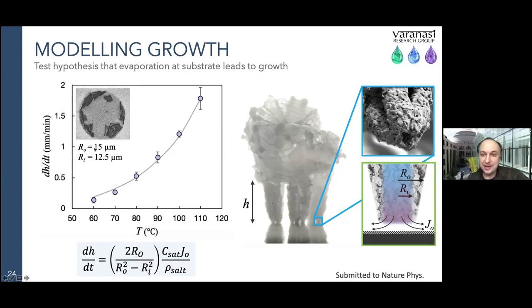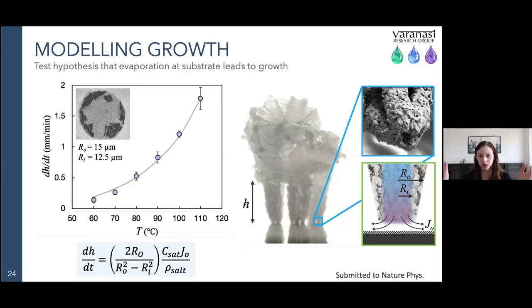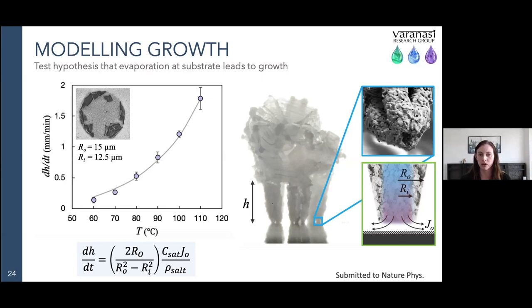A question from Ramiz Iqbal: in the first part describing the fingering instability, why don't the crystals come closer and aggregate? Normally for microparticles one might see close packing after complete evaporation. In the colloidal case you have a liquid bridge which brings them together. But for this crystal formation and fingering instability, the crystals are forming due to the evaporation — they're not already present in the fluid. Looking from below using a clear glass substrate confirmed that the crystals aren't forming before the retraction; they're forming after the drops pinch off already. So you don't have the same liquid bridging effect bringing them together, because by the time they form, the interface is already gone.